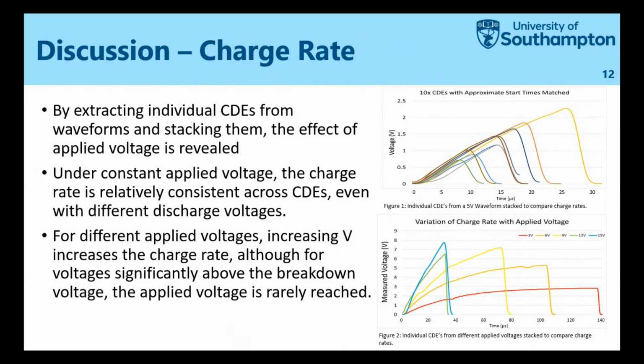The second graph shows 5 discharges that I've plucked out at a maximum value from a long waveform. This is me picking out the highest one I could find, but at higher applied voltages, the maximum discharge voltage actually doesn't reach the applied voltage, because it's breaking down around the breakdown voltage. And you can see that the charge rate varies with voltage as well.